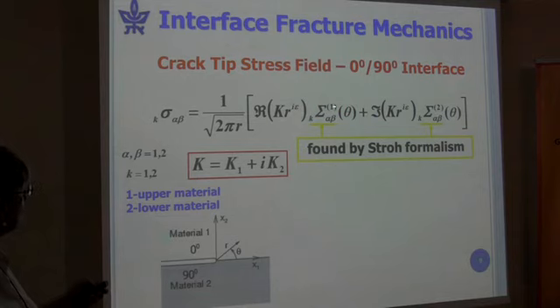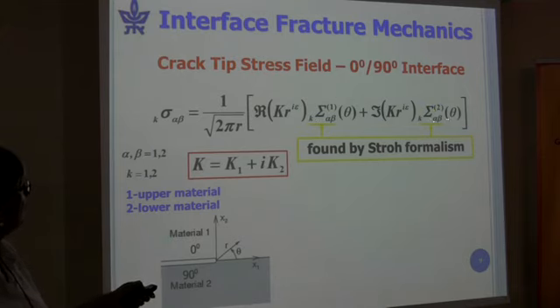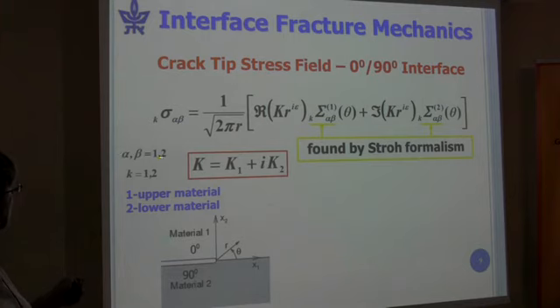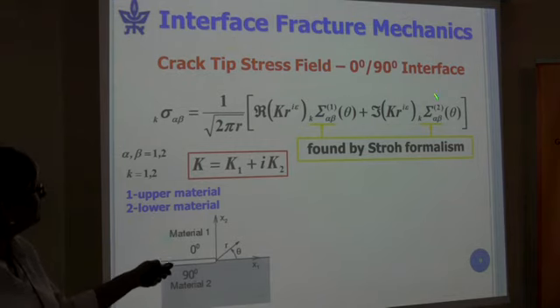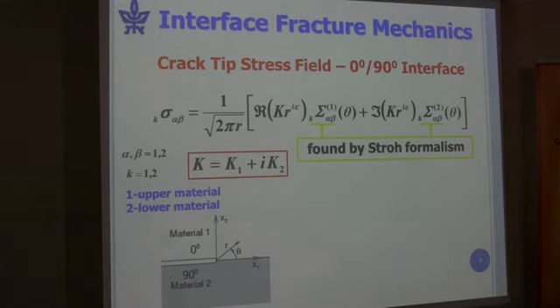Now, these functions, which are nice functions, they're bounded functions of theta. We have one for mode 1, one for mode 2. They have to do with whether we're talking about sigma 1,1 or sigma 1,2, and it depends whether upper or lower. And we have analytic expressions for these. They're not numerical, and we get them from the Stroh formalism. And as I said, epsilon is called the oscillatory parameter. It's causing the stresses to oscillate.